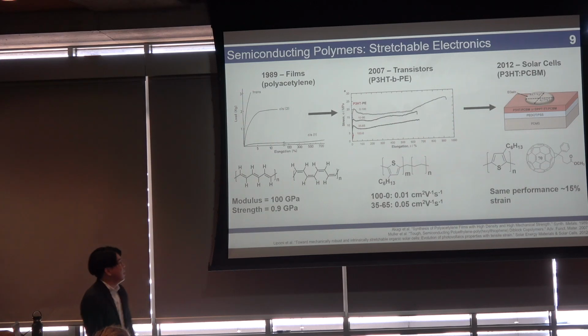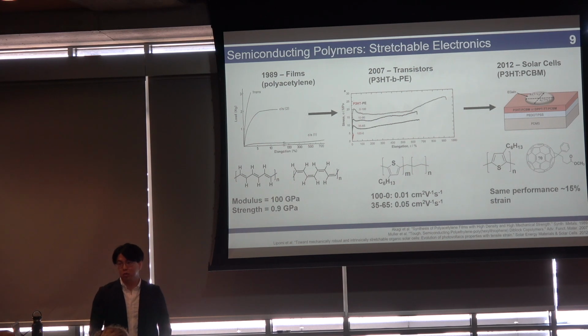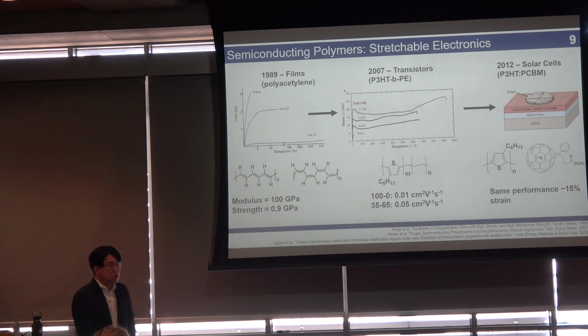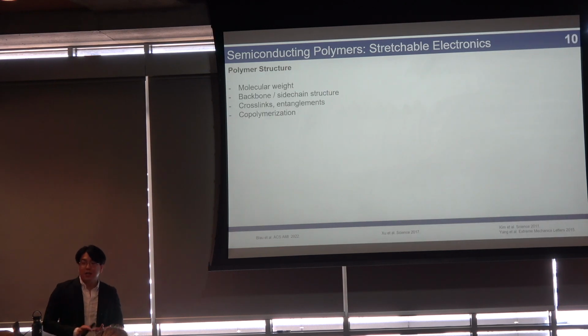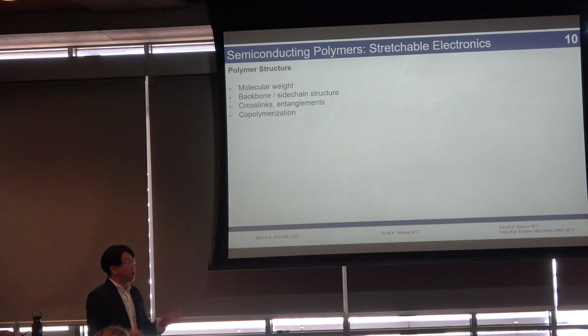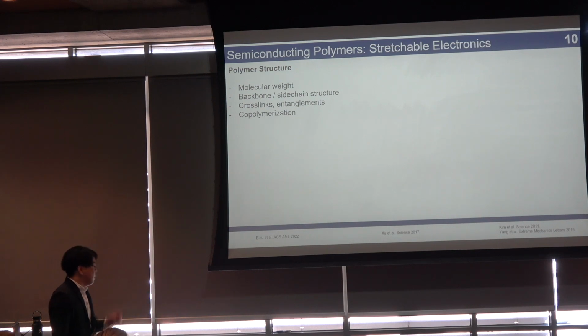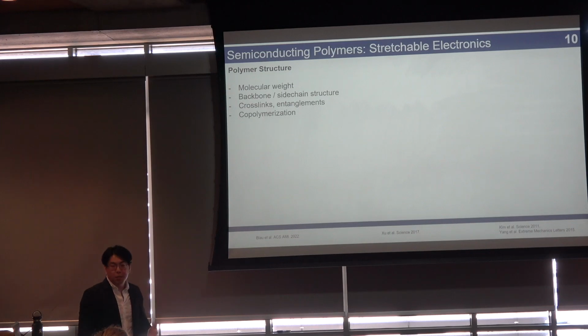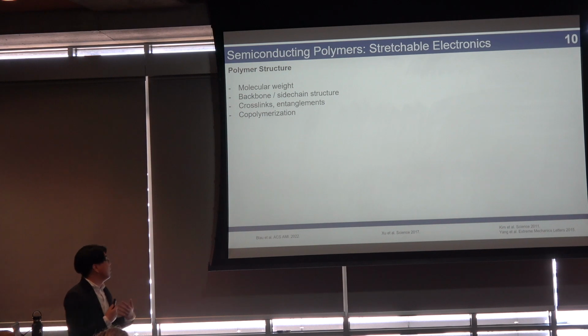So this is actually work done by my advisor, Darren Lipomi, during his postdoc at Stanford. And the group figured out that, well, if you make stretchable solar cells from these conjugated materials, you could get the same device metrics at 15% strain relative to 0% strain. So you can actually stretch these materials quite a bit. And this has given rise to a whole field of stretchable electronics, and we've gotten very, very, very good at this. We have a very deep understanding of how to improve the polymer structure to make these polymers stretchable.